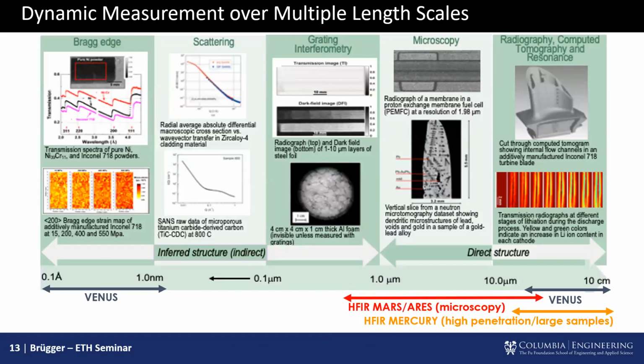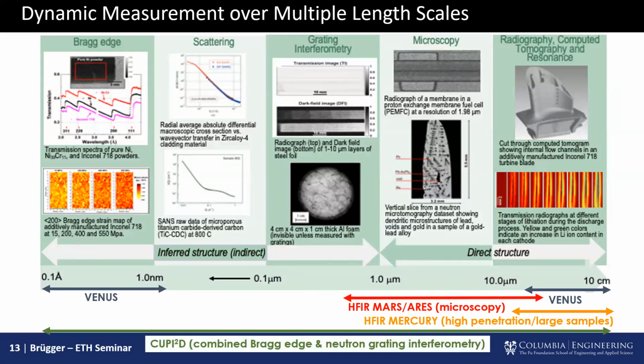You can imagine now we are looking at an area detector. So just like a photoplate or just like an X-ray tomography detector. So you're looking at essentially a photodetector that detects neutrons instead of photons. And with this source of neutrons, we can actually measure across multiple length scales. We can measure on the atomic scale to get an equivalent measurement of what I've shown with neutron diffraction, but in this case, imaging, where we get one scalar strain through the sample for every picture that we take. We can do grating interferometry, which I'll also show in some more detail, where we're actually doing small angle neutron scattering using diffraction gratings.